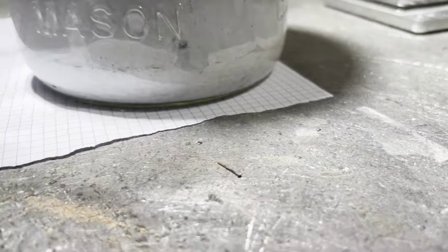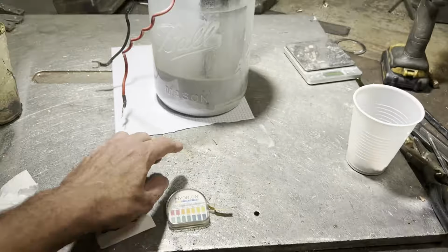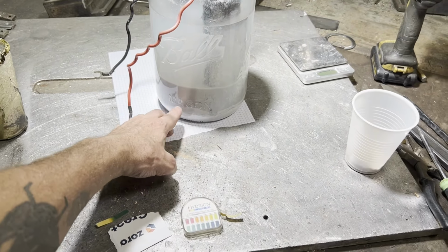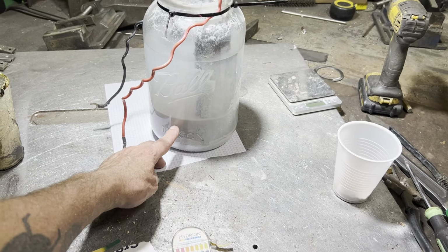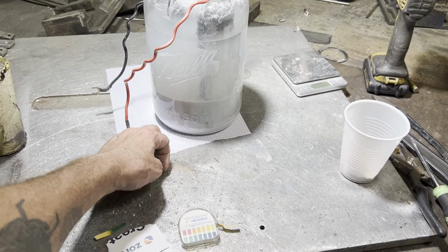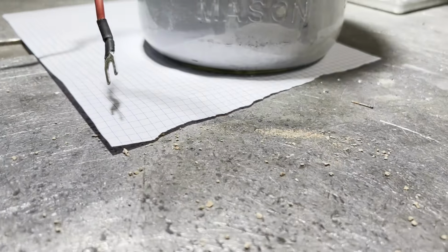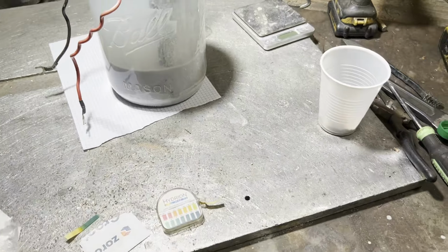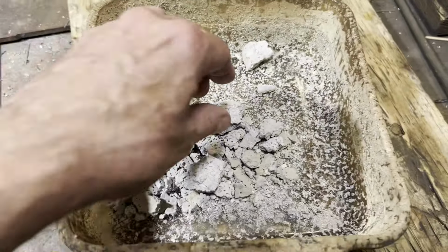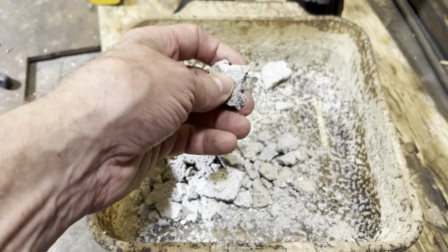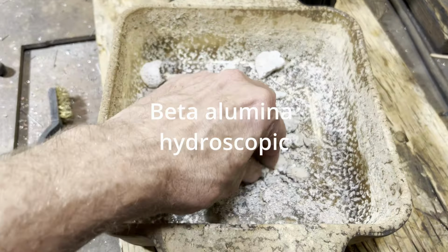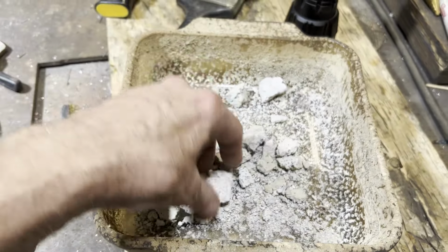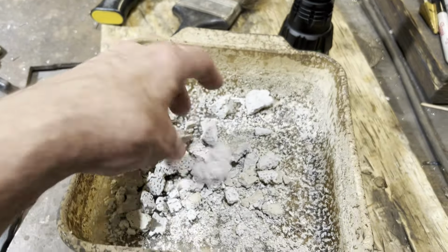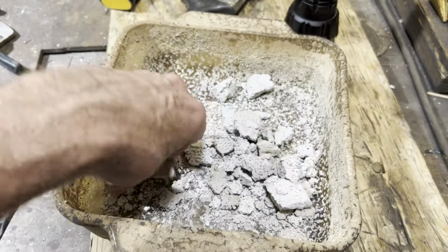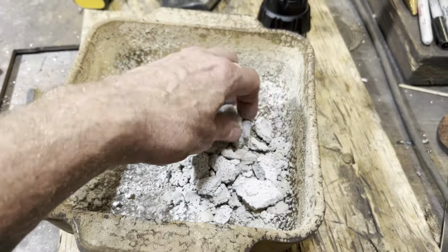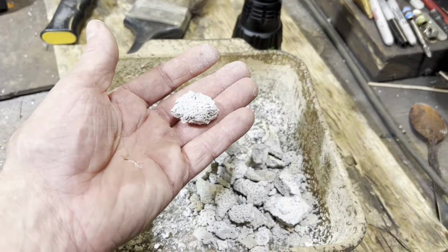We have two different phases here. This is 1.6 amps and this is about 3.4 amps. So we're looking at the corresponding energy densities. And it would appear that the lower the energy density, the less aluminum contamination you get. This stuff's still kind of wet. I guess it feels like it. Maybe not. So I'm definitely not going to grind this stuff up before I calcine it this time. Probably better to leave it in chunk form so it's not all just blowing out of the crucible on me.